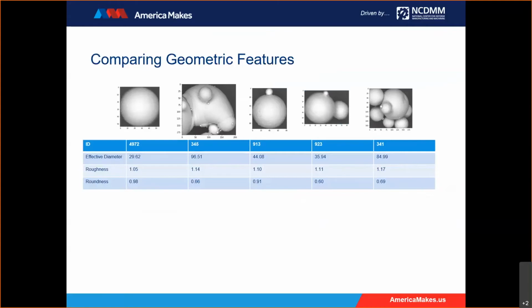One of the morphological features that we're particularly interested in is particle roughness. Generally, particles with spherical shapes and smoother surfaces flow easier than those with rougher surfaces and irregular shapes, because the higher surface roughness induces more interparticle friction and mechanical interlocking, which decreases flowability. If you take a look at these particles at the top, you can probably tell that some are rougher than others. On the left, we have a virgin particle, and next to it, what looks like spatter. Then we have particles with more and more satellites going to the right.